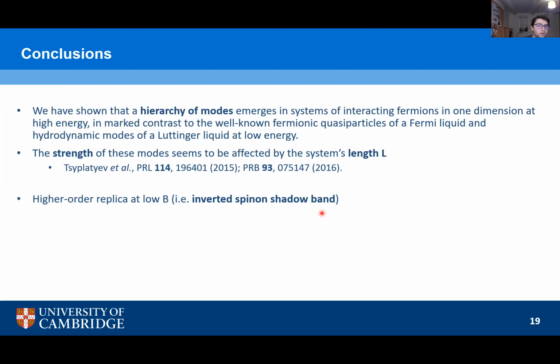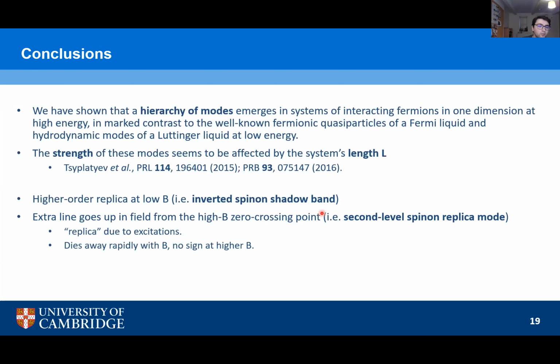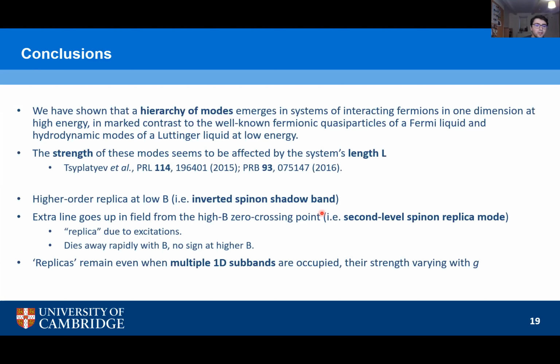We've observed a first level replica at low field, the inverted spinon shadow band. We've also observed the second replica at higher fields, a second level spinon replica, which dies quickly away in momentum. If you want to be optimistic, a hint of a third replica as well. And then these replicas remain even when multiple 1D subbands are occupied, and their strength varies with G.